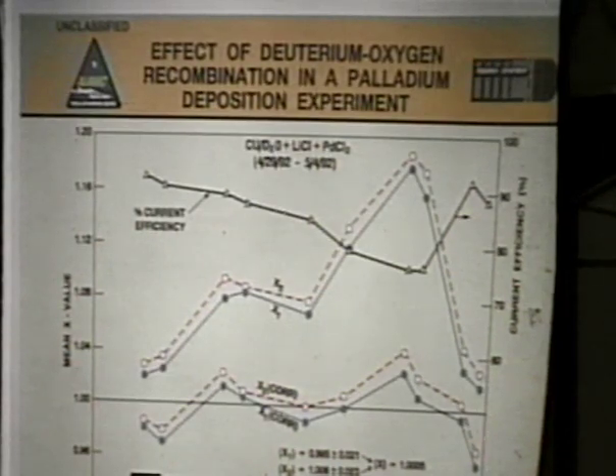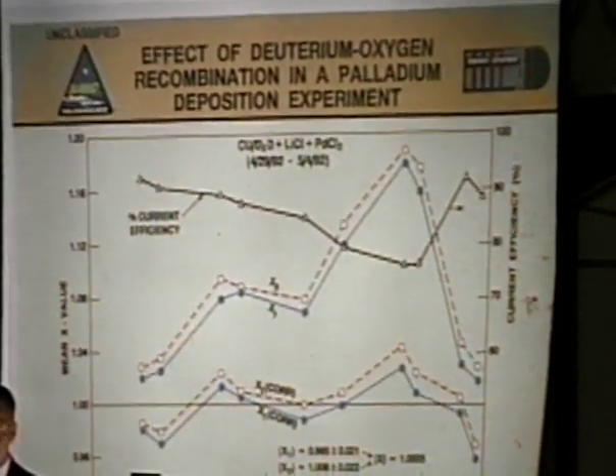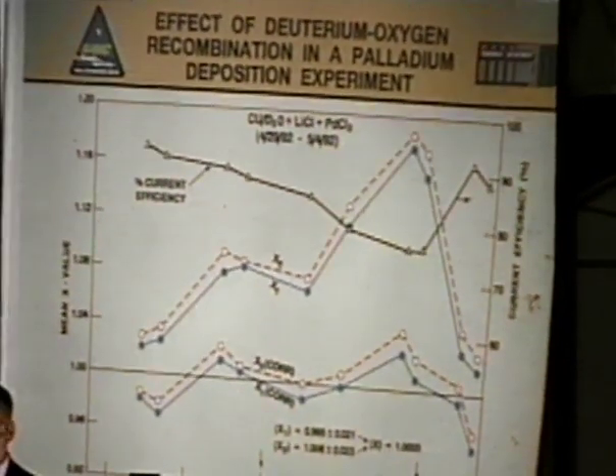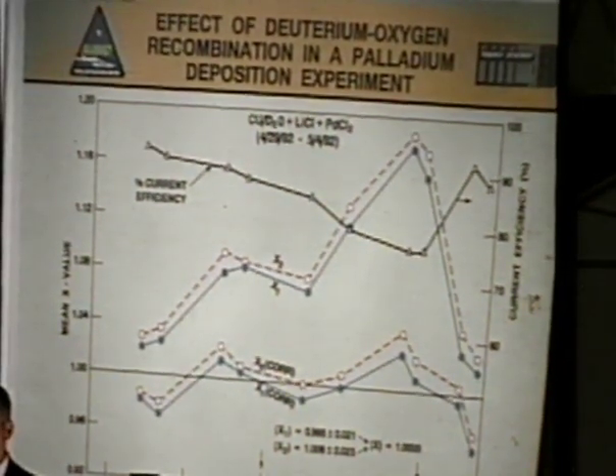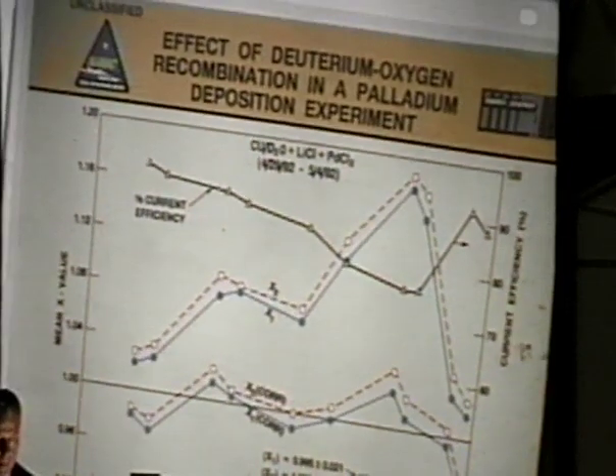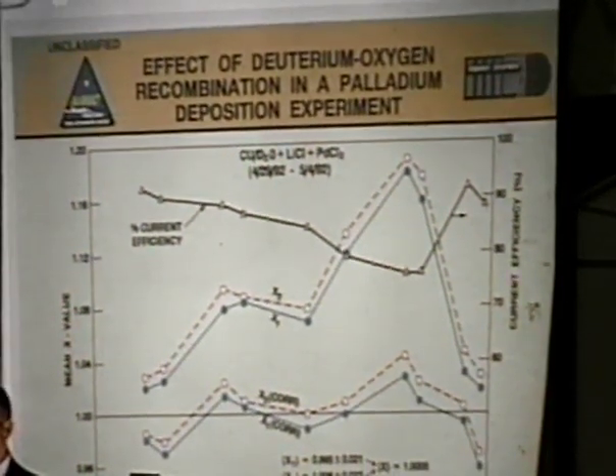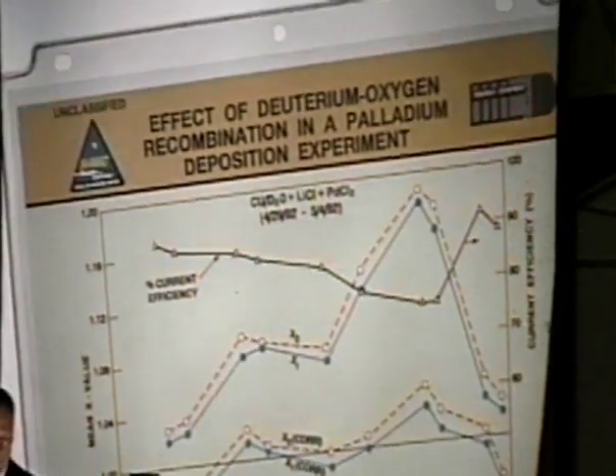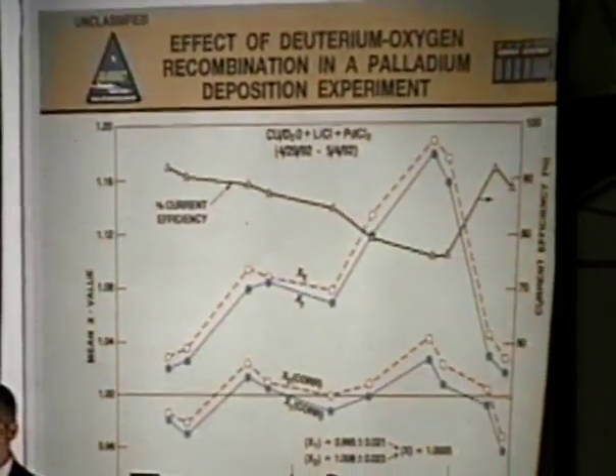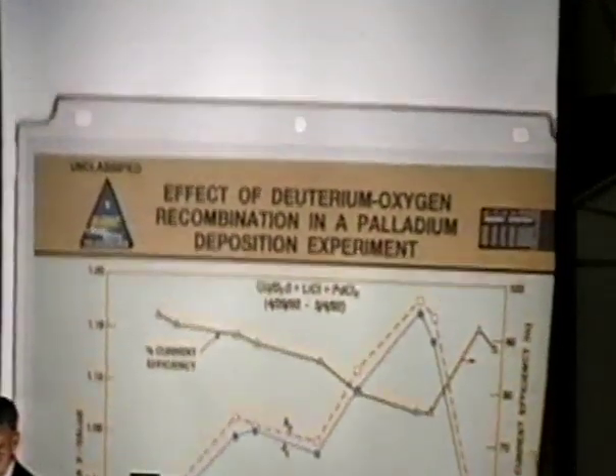So when there is recombination, we detect it, and we can correct for it and get good results, as you see here. So recombination is not an issue. We can tell when we have it, and we can correct for it when we have it. But using a palladium cathode that's fully submerged, we never see recombination. Now, Steve Jones has recently made a big issue of this. He'll have a paper coming out, but he has no basis for his argument of recombination.